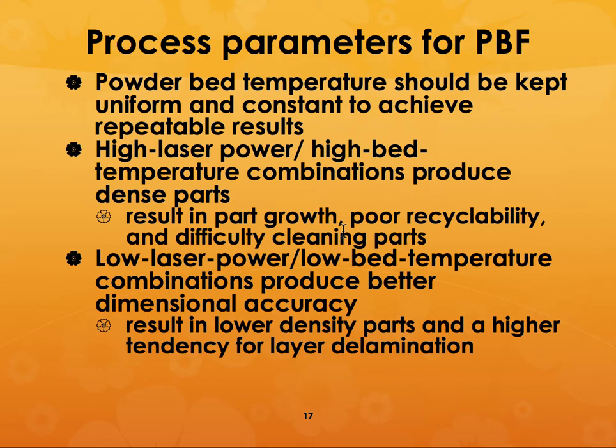Once the parts are formed, the grains can grow and the parts can grow. And whatever remaining powders are there, you can't recycle them very easily, and it is extremely difficult for you to clean the parts. So you may have to end up having to do final machining of the part. But if you use low laser power and low bed temperature, it produces better dimensional accuracy, but it will produce lower density parts and a higher tendency for layer delamination because those layers cannot bond well together.